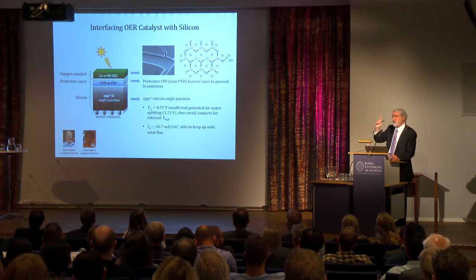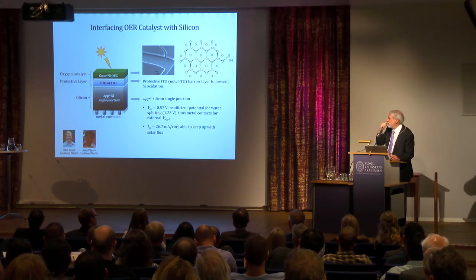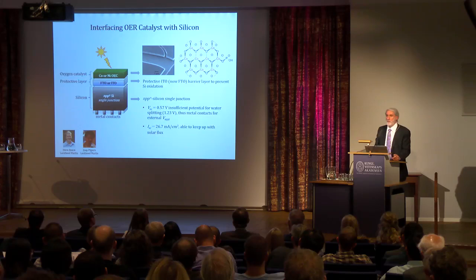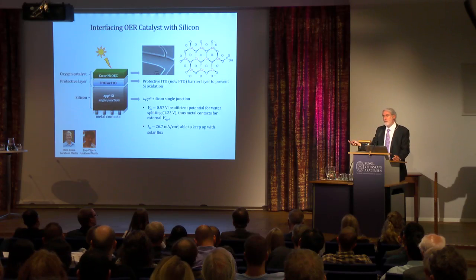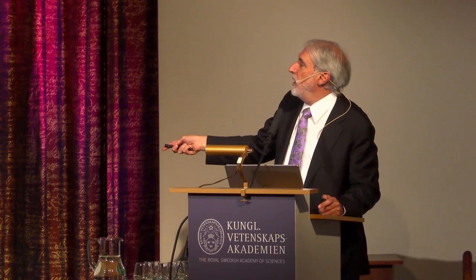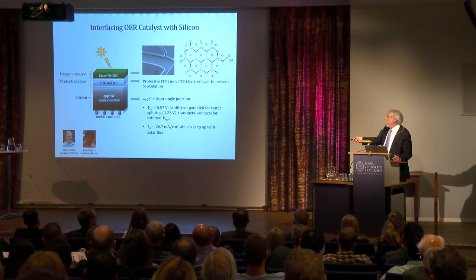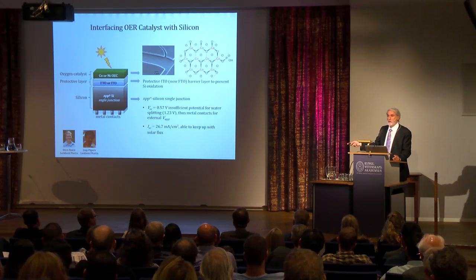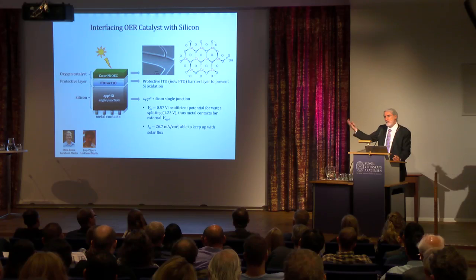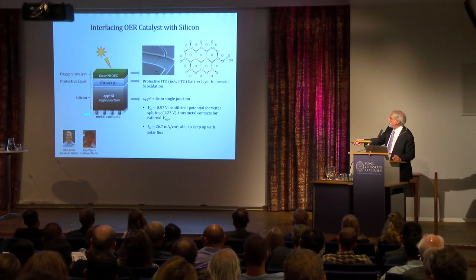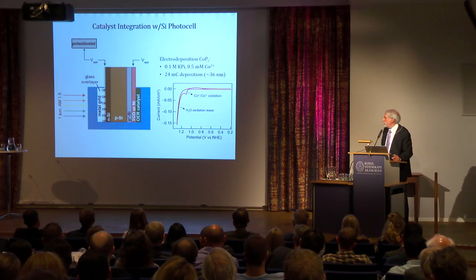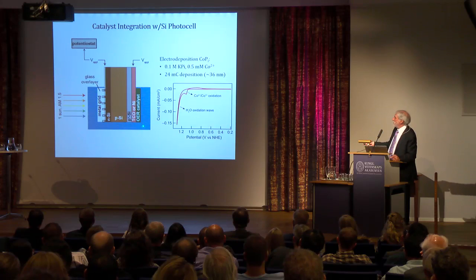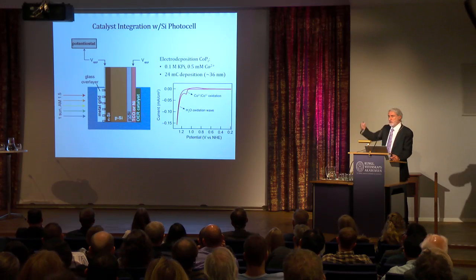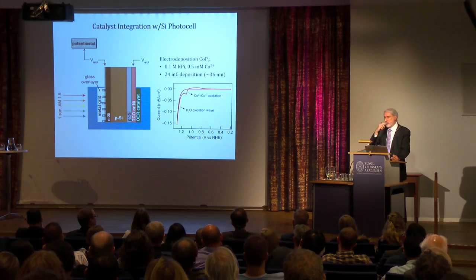Now, silicon, a single junction, one flavor of silicon, puts out 0.57 volts. Water splitting's 1.2 volts. So in this configuration, if I use a single junction, I don't have enough voltage to split water because I only have 0.6 volts when I need 1.2 volts. So we had to put contacts. We did this in 2011 and put contacts here so we could put extra voltage into the silicon. And then we just dropped it in water, and we did what I told you before. In Co-Pi, we just have the silicon now with our catalyst, or our coating.